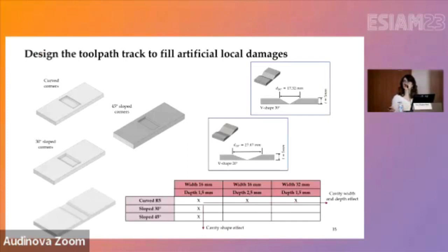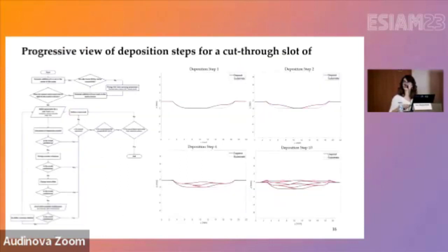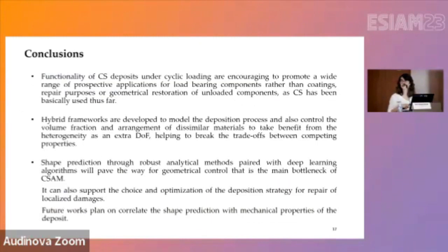So we have considered some local defects, let's say enclosed or through defects, or even welding of different geometries. And we have started implementing the analytical code in order to design the trajectory for repairing, in order to minimize the time and minimize the excess material that should be removed after repairing. And the next step would be to correlate this geometry to the mechanical properties or physical parameters of the structure.